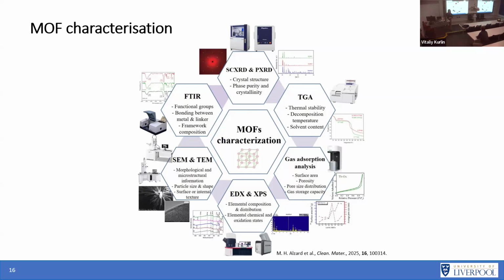So in this, we'll put it inside our gas sorption analyzer, and you will dose it with a certain gas, whether it's nitrogen, carbon dioxide or something like that, at different values of relative pressure. You'll get an associated isotherm, and that will determine, based on the amount that you have put in there, whether something is high surface area, low surface area, and what kind of porosity it has.